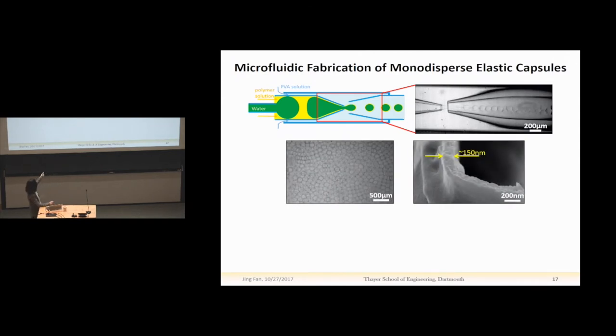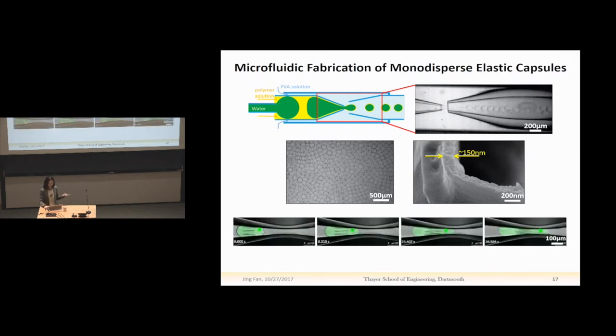So this is a monodisperse capsule that we obtained, and we also characterized the thickness of the shell, which is about 150 nanometers. And we can precisely control this thickness by changing the concentration of polymer in the middle phase or changing the flow rates. And because we want these capsules to transport freely in a porous medium, we use an elastic block copolymer, and we characterized that this polymer is highly elastic. So the resultant capsules are also very deformable, and we show that they are able to pass through a constrictive channel with a throat size smaller than half of the capsule diameter, without releasing their cargo.